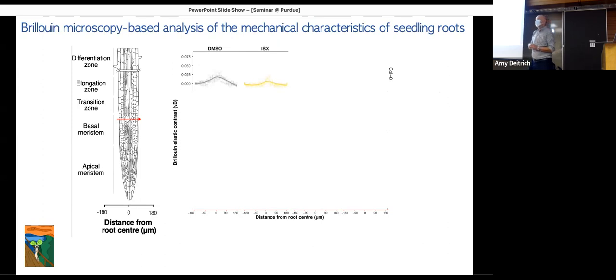Now what you can see is that in the isoxaben treated one, the level of the stiffness has reduced in the central cylinder, which is what we would expect if, for example, the stiffness is mainly driven by cellulose. Then we got a bit of a surprise. If you do the same with sorbitol treated seedlings, where you have reduced the turgor pressure, apparently the stiffness in the central cylinder area is also reduced. There are discussions that cell wall stiffness is directly or indirectly controlled by turgor pressure levels. So what we see here could be supporting this hypothesis, that if you lower the turgor pressure level, the cell wall stiffness is also lowered because there's not so much pushing anymore.